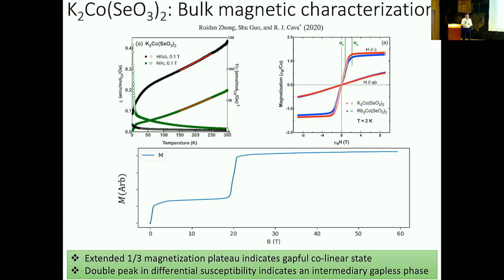And so that's very different from what I showed for the spin chain. And in some ways, it is a more natural behavior because the system has, let's say, an incompressible state in some significant range of applied magnetic field, and then an additional incompressible state here. And then in between, we've got this range where the system is developing and changing its magnetization.